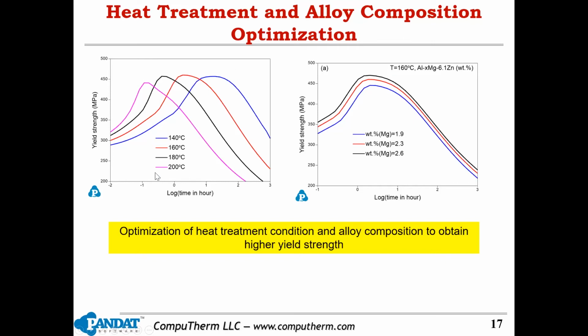So with these virtual experiments, you can select the best aging temperature to reach the highest yield strength with the shortest time. And in the right figure we basically show the alloy composition can also affect the yield strength. So with this type of virtual experiments, we can optimize the heat treatment condition and also alloy composition, right?